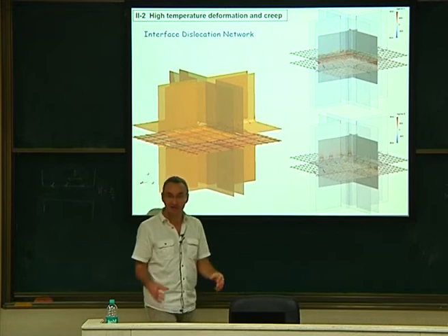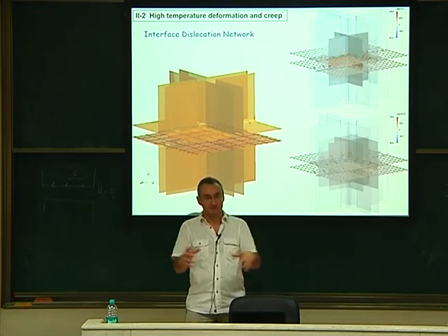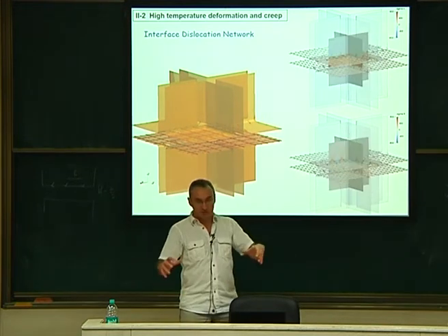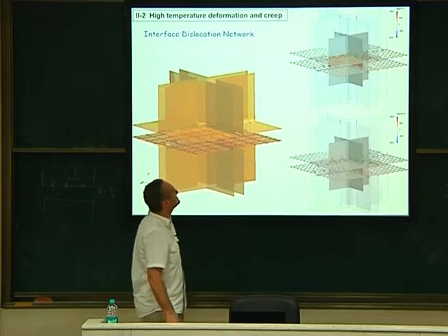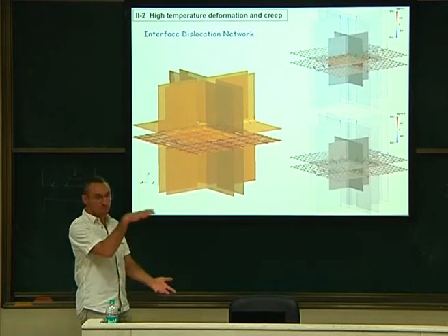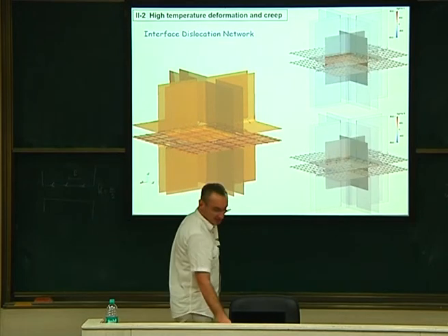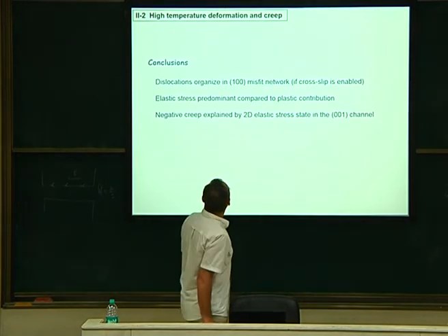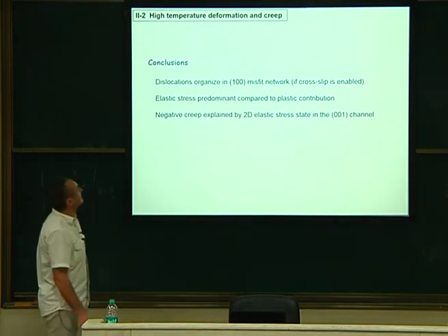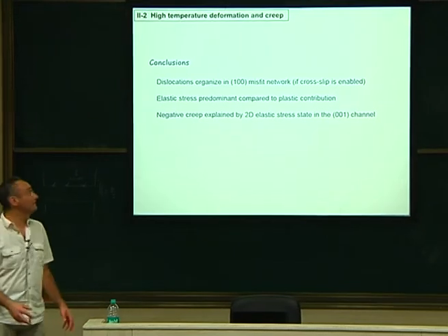Okay, so you get the idea. Just because you are pulling a lot in the horizontal channels, then you are shrinking your specimen, and this in some cases could be bigger than the plastic part at that stage. So this was the conclusion for these two studies, I would say.